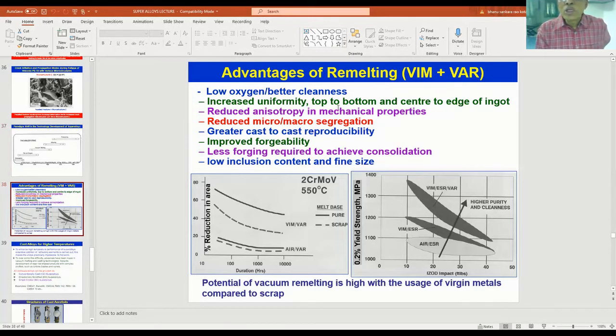Increased uniformity, top to bottom and center to edge of the ingot, uniformity in composition and structure, reduced anisotropy in mechanical properties because the material is more homogeneous. There is no segregation at all. There is reproducibility from cast to cast. Always it is not possible to produce material of 100 tons or something like that. We have to use furnaces of 10 tons, 25 tons. Therefore, there will be 4 casts in 100 tons. So reproducibility should be there in composition from one cast to the other. It is possible by employing these processes.